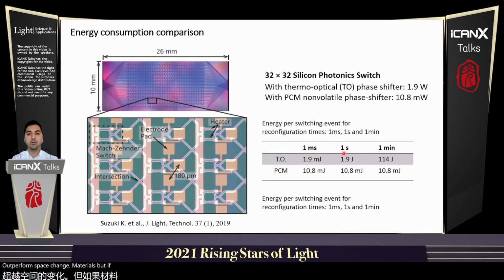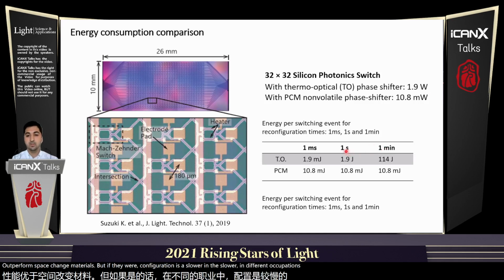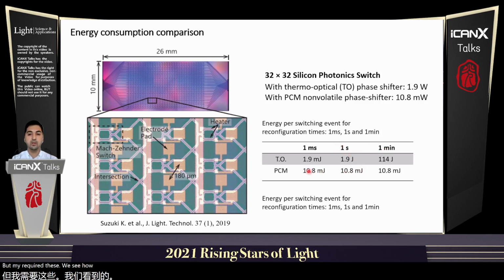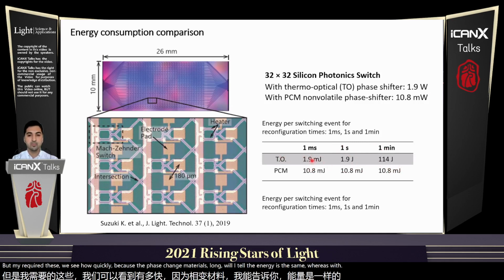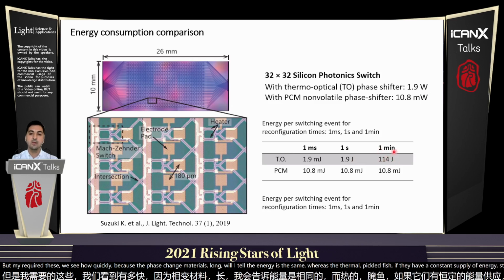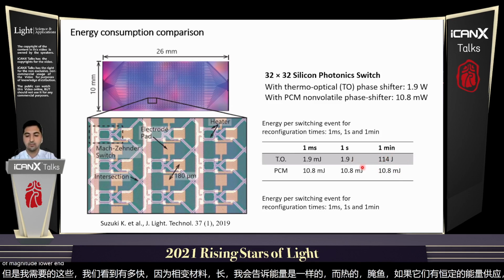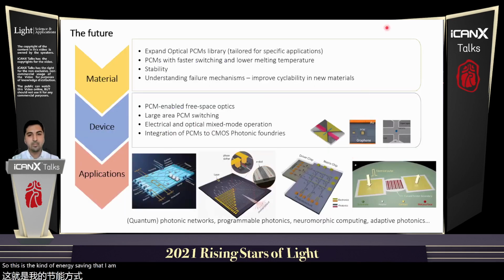But if the reconfiguration is slower and slower, in different applications that might require this, we see how quickly, because the phase change material is non-volatile, the energy is the same, whereas the thermo-optical phase shifter has a constant supply of energy that starts increasing really fast. After a minute, we are already 4 orders of magnitude lower in energy. So this is the kind of energy saving that I'm talking about.